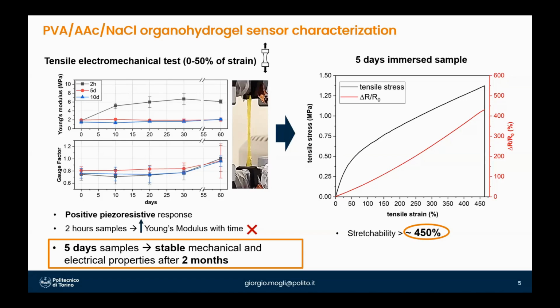So the red one is the piezoresistive positive curve, which shows three linear ranges in which the gauge factor could be computed, and is similar to the others found in literature regarding ionically conductive hydrogels.